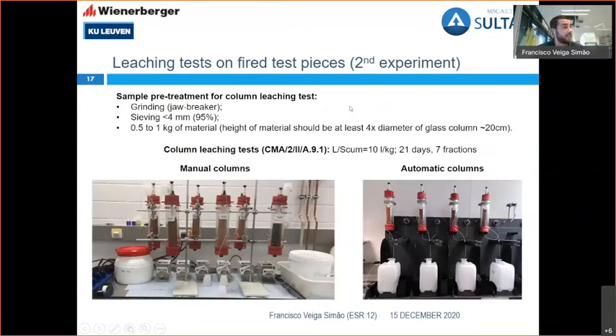This cannot be closed with the leaching test, the environmental legislation test that you need to do when you produce a shaped material. Here, as you might know, you might think there was an error by me, but indeed we are doing column leaching tests, which are leaching tests for granular material, and for shaped materials we should follow the diffusion test.